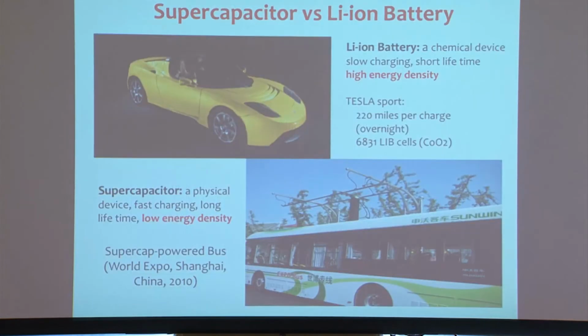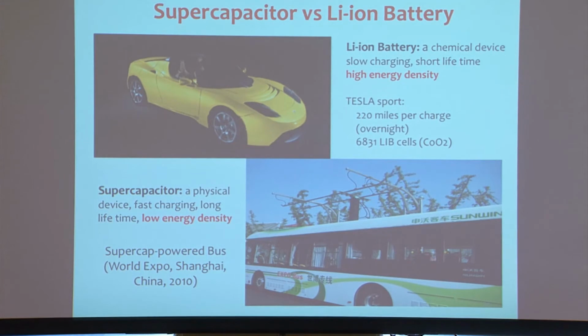Here is a Tesla, powered by lithium battery, the old generation of lithium battery. You charge it overnight, and you can drive it for perhaps 200 miles. Here is a bus powered by supercapacitor, about 9 years ago in Shanghai. You have to charge it every 500 meters, every stop, but you charge it within seconds while you load and unload passengers. The reason is that supercapacitors have a low energy density, but can be charged in a very short period of time.